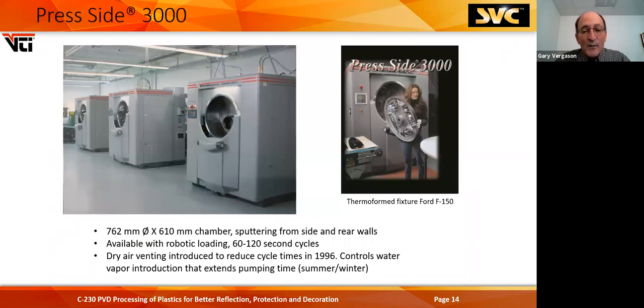Systems evolved a little bit more. We added sputtering capabilities on the sidewalls as well as on the back wall. These systems are also available with what we called a gantry loader, an overhead robotic loader that would lift the heavier fixtures out, spin around, and put the other fixture in and start the cycle. These still ran a 1 to 2 minute cycle time.